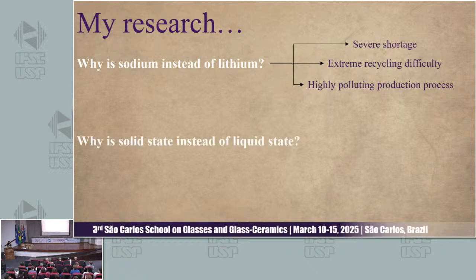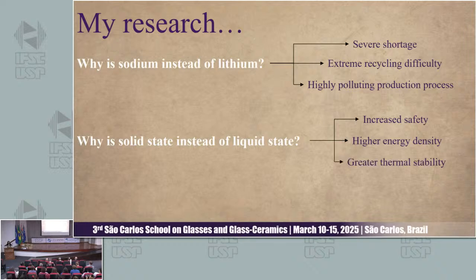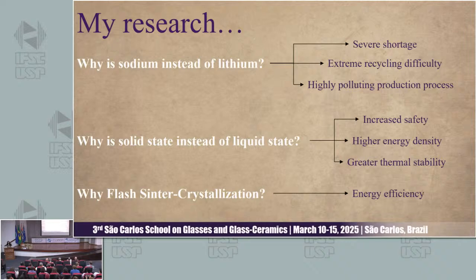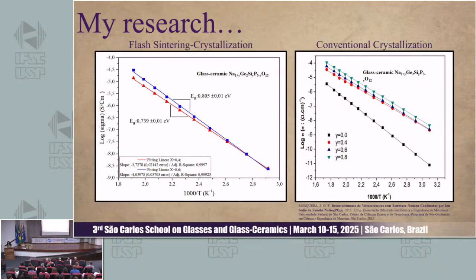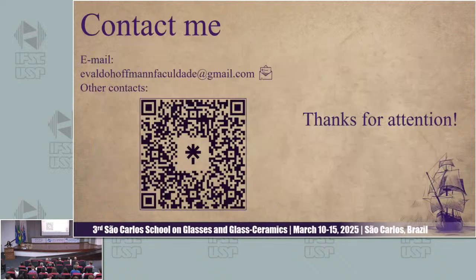And why solid state instead of liquid state? Because solid state increases safety in comparison to liquid state, and obviously offers high energy densities and great thermal stability. And why use flash sintering crystallization to prepare the material or the phase? Because flash sintering crystallization is very energy efficient compared to the conventional process. My preliminary results show we can obtain similar conductivity values for the flash sintering crystallization compared to the conventional crystallization. For more details, I invite anyone to my poster.